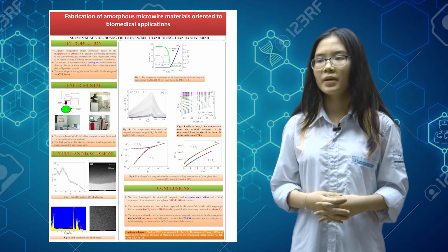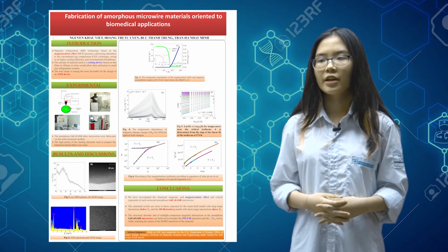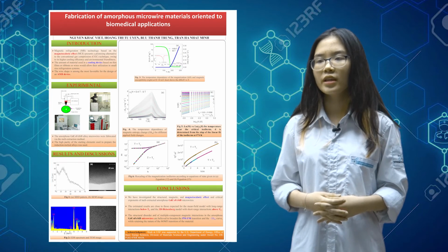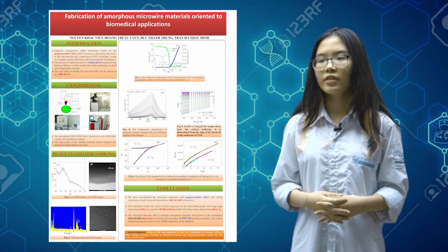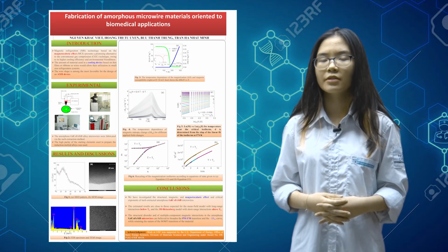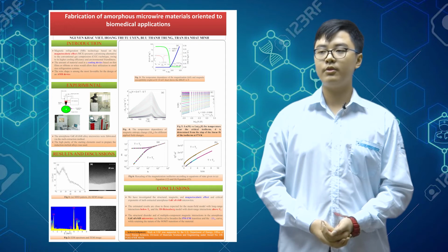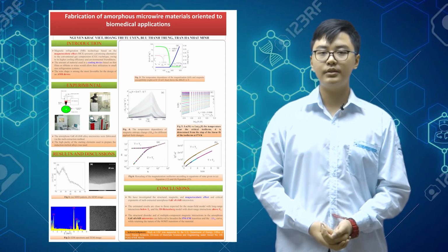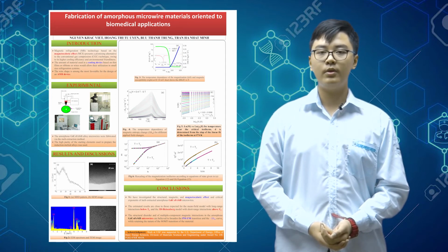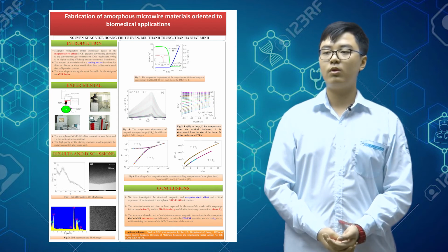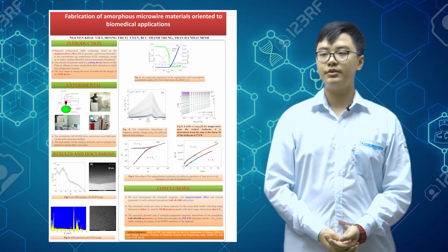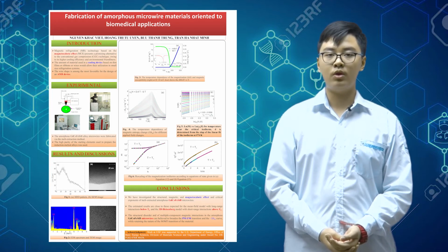The inverse susceptibility as a function of temperature, chi minus 1 of T, generated from the M(T) curves in the paramagnetic region, is also shown in this figure. Its linear temperature dependence is consistent with the Curie-Weiss law in the paramagnetic region. Figure 4 shows the temperature dependence of the magnetic entropy change delta SM for different applied field changes. The magnetic transition becomes broader with increasing applied magnetic field up to 5 Tesla. The largest changes in M with respect to T occur around Tc.